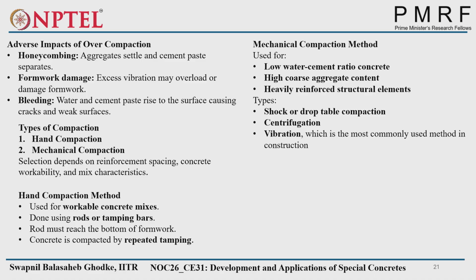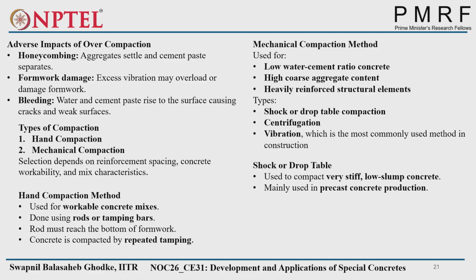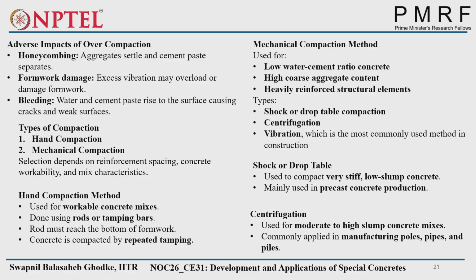Three types of mechanical compaction are available: shock or drop table compaction, centrifugation, and vibration, out of which vibration is more popular. Shock or drop table is generally used to compact very stiff and low slump concrete, mainly in precast concrete production. A table will be there, and we put the concrete into some cube or formwork. The table lifts through some distance and then drops, like the flow table, with a certain frequency and amplitude. That creates vibration in the concrete and gives compaction.